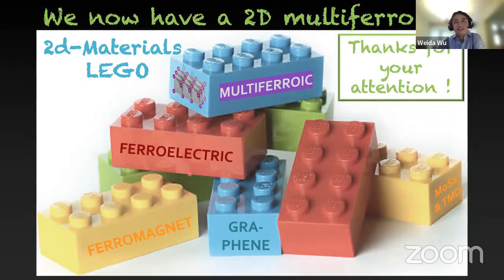Or is it known? I'm sorry to ask. Yeah, I think for nickel bromide there were some. To measure it, to switch it, to apply a field and do, I don't know, piezo force microscopy, it's very hard. Also, in our case, I think Riccardo Comín and others tried, of course, to contact and switch, which would be the real smoking gun of ferroelectricity, but it is very hard to contact a monolayer. But with this symmetry analysis, you can see where the symmetry is reduced, along which direction you have symmetry reduction. So you can have sort of indirect but still strong proof that ferroelectricity is there. But I don't believe that yet, for example, the quantification of polarization is available in the literature.